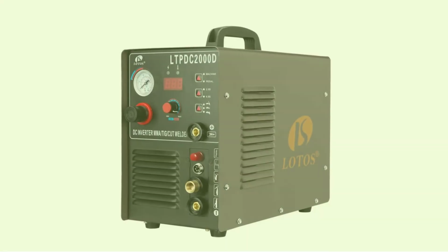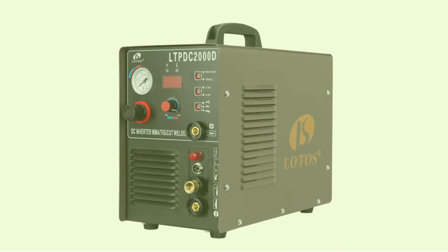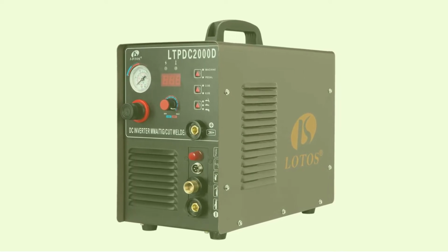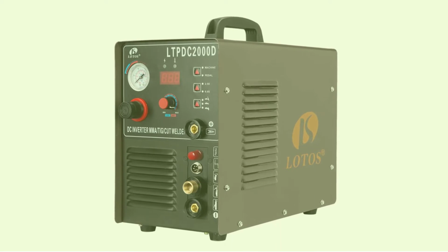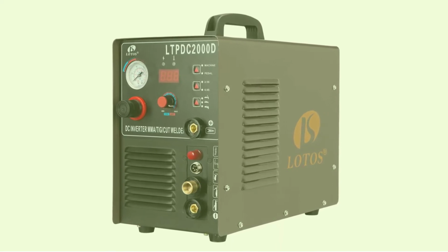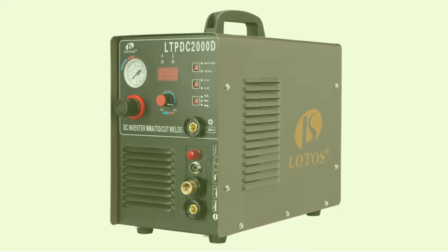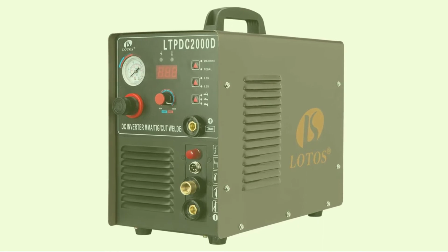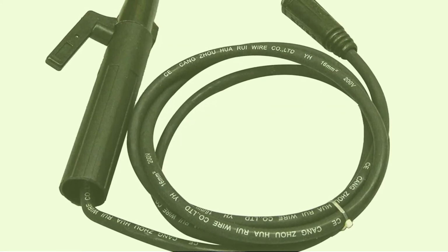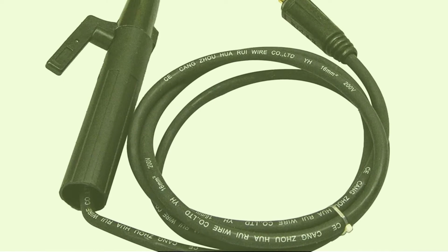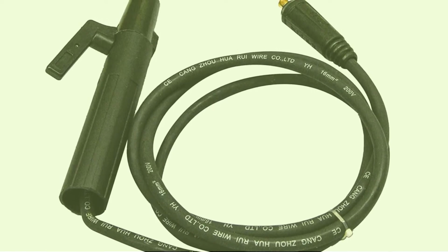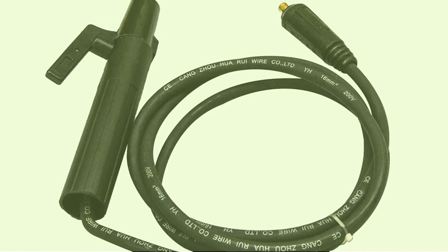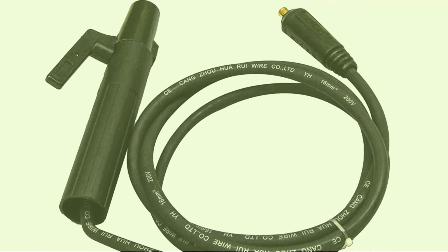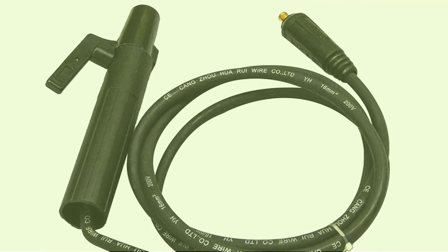LOTOS LTPDC 2000D non-touch pilot arc. Most of the time, a welder joins metals, but sometimes operators want to slice them apart or perhaps cut out a hull or design. A plasma cutter is arguably the most efficient way to do this. Usually that means buying a separate machine, but with this unusual LOTOS welder, it's included. So, in addition to TIG and stick welding of up to 1/4 inch thick material, the welder can cut through mild steel up to an impressive 3/4 inch thick.